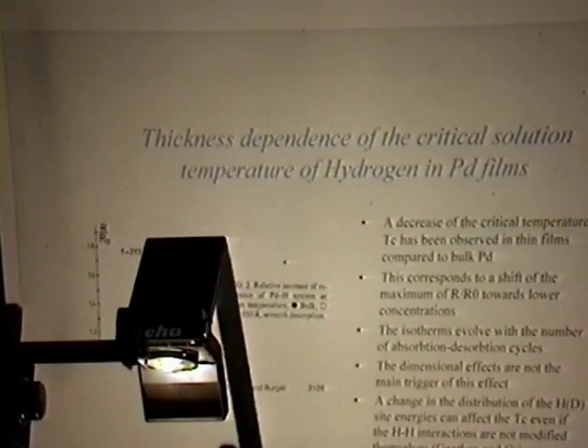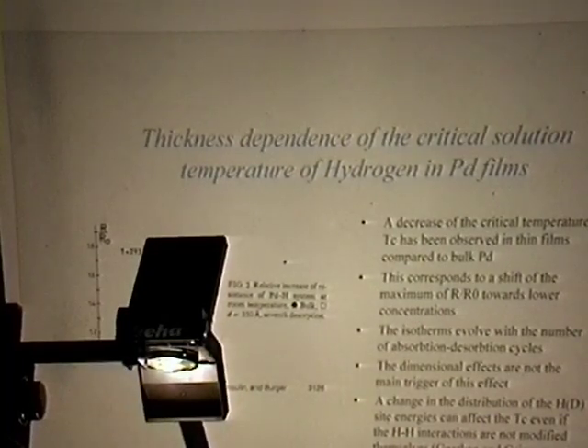This is the relative increase of the resistance for a bulk sample, in this case for 550 angstrom films. It was found that the isotherms evolve with the number of cycles of absorption and desorption. The first thing that came to mind is a dimensional effect due to the electronic property of the medium, but the electronic property of the medium reaches a stationary state after a few hundred angstroms. We are talking about 1,000 angstroms of sample, so it must be something else.